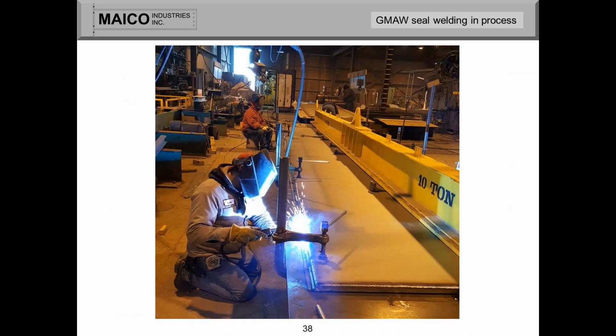The next photo here is one of the deck with the cap plate on now, and our welders are busy welding. We utilize gas metal arc welding to seal weld these deck panels, and in this case, we utilized 1/16 diameter metal core wire to complete the nearly 130 linear feet of fillet welds needed to seal each one of these decks prior to the injection process. And I should mention this is an E70 C series wire electrode certified to both AWS and CWB standards.